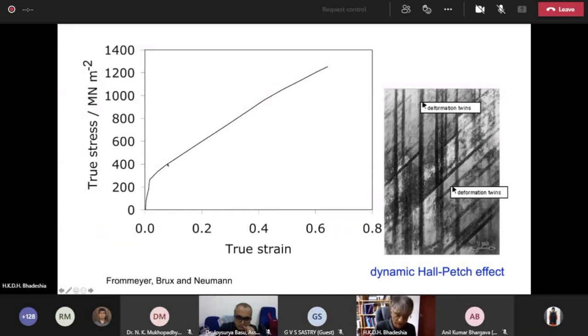The reason why we get this nice work hardening, which delays plastic instability, is that as you deform, you get mechanical twinning of the type illustrated here. And that mechanical twinning divides up the parent grains into ever smaller grains. So effectively, that gives you work hardening because you need to think about this like a dynamic Hall-Petch effect, where you're reducing the grain size by partitioning the grain with these mechanical twins. So on the face of it, it has excellent properties.